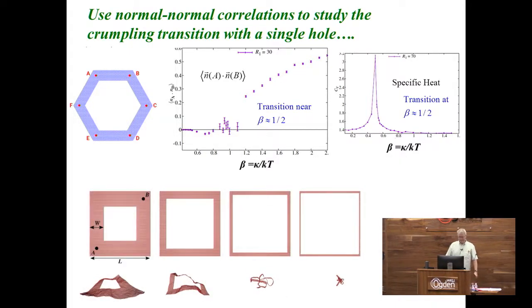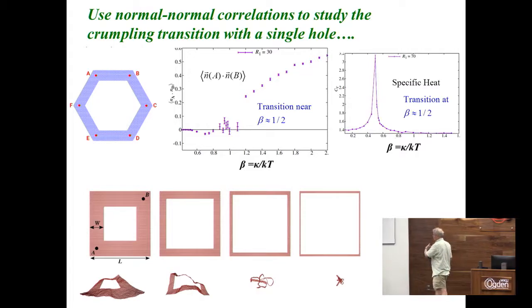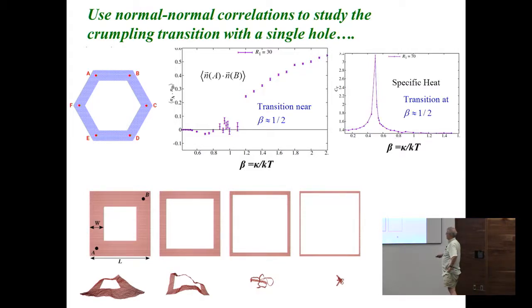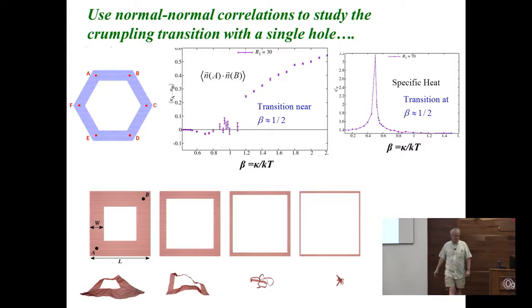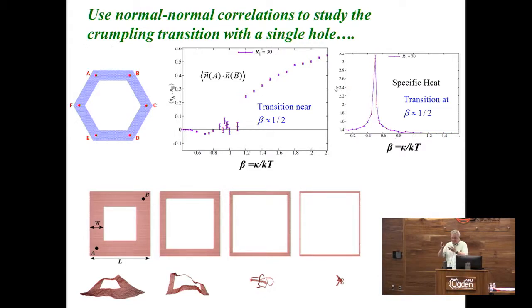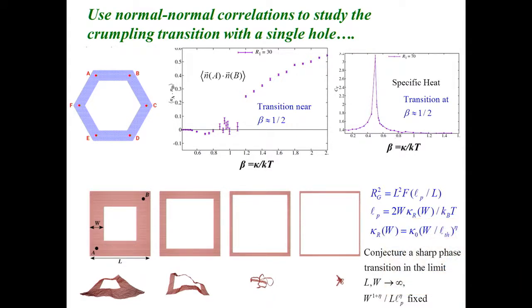So to summarize, someone asked what about the size of the hole? Well, you can vary the size of a square hole, for example, and you go from this flat thing where the tiny hole isn't going to make a big difference. You put a pinhole in a piece of paper, it doesn't change it. Make it big enough, it seems to crumple, and we actually think, although it sort of looks like a ring polymer in the end, it does. If you take the thermodynamic limit and study the size, which the fancy name is the radius of gyration, and put in the appropriate scale-dependent bending rigidity depending on the width of the frame, we think that in an appropriate limit of L going to infinity, that's the width of the frame going to infinity, with this eta-dependent ratio fixed, there may be a sharp phase transition.